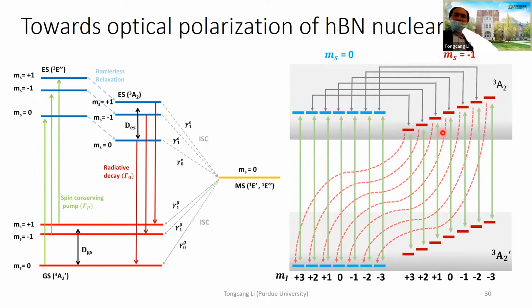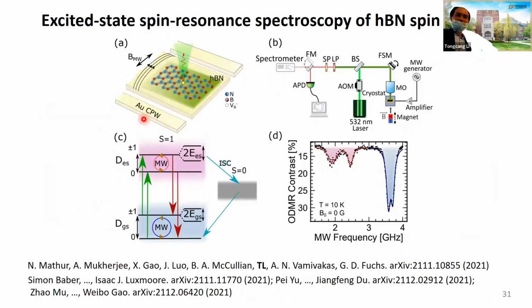But to do that, first of all, we need to make these energy levels degenerate. To do that, we need to know the D of the excited state. Recently, we collaborated with Professor Fuchs at Cornell University, and they used our sample to perform this measurement. They also put the hBN on a plasmonic waveguide and measured at low temperature. In addition to the ground state electron spin resonance at 3.5 gigahertz, we also observed an electron spin resonance around 2.1 gigahertz, and that's due to the excited state.